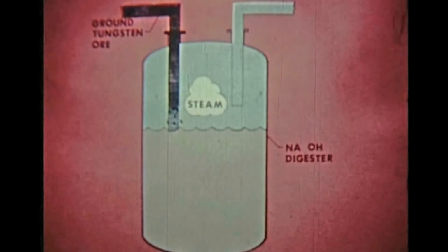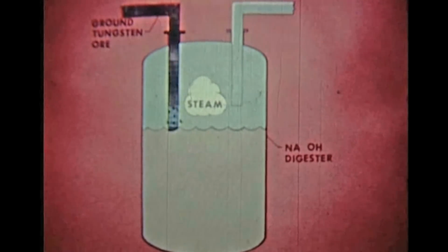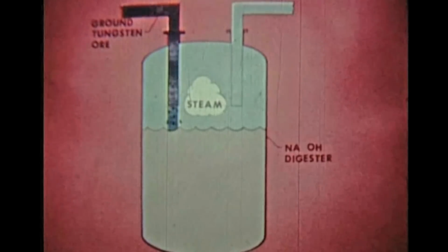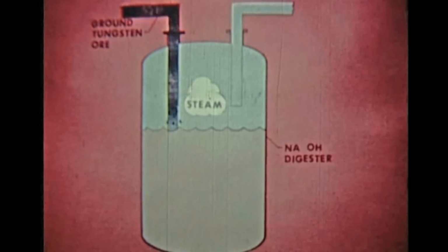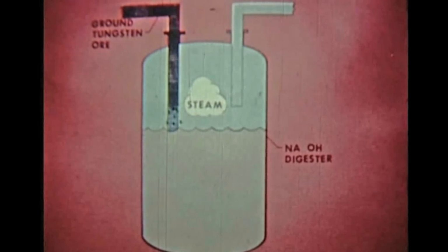The fine particles are transferred to a steam-heated pressure vessel where they are mixed with caustic soda, heated, and agitated until the chemical reaction is complete. The mixture is then filtered in large drums with porous coatings to remove the solids, which are scraped off and fall into a chute. The liquid sodium tungstate passes through and is pumped to a large cypress tank where it is agitated and calcium chloride is added.